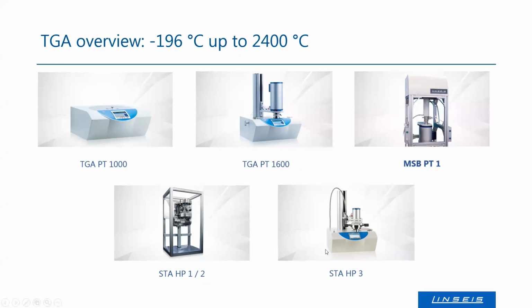And then we have the pressurized systems. You can see in the lower line, the STA HP1 and 2, which is floor mounted for simulating reactor conditions, high pressure analysis up to 150 bars in the temperature range up to 1600. And if you decide to go up to 1000 only, we have the HP3 system. It's a tabletop pressurized system.